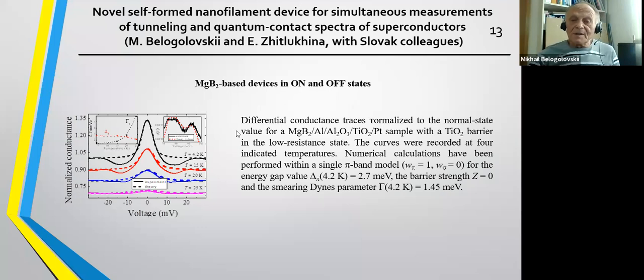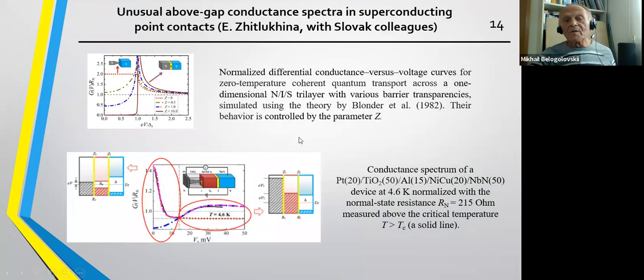So it was done and such a structure was created, and the results are optimistic, but we need to continue this study. It is able to switch between the two regimes and to perform measurements with the same sample in the two regimes, and after that to compare the results between them. And the last one, again with Slovak colleagues, was the explanation of some unusual features often observed in superconducting point contacts, in particular some above-gap conductance spectrum.